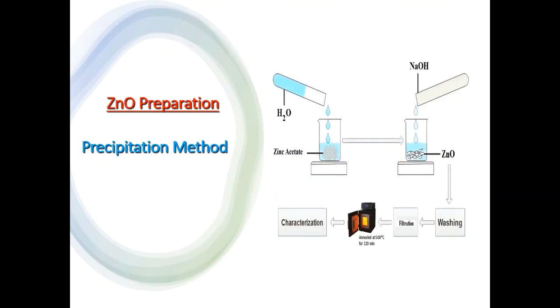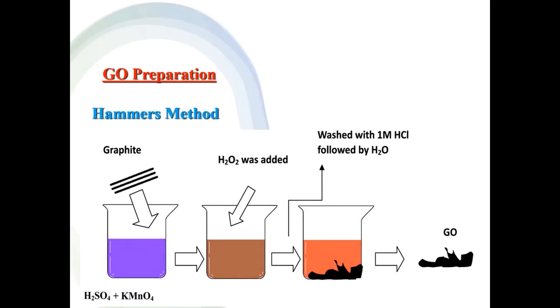So to achieve our aim, we prepared our samples as follows. For nanomaterials preparation, the precipitation method was used to make zinc oxide with zinc acetate as a metal salt and sodium hydroxide as a precursor. Also, graphene oxide was prepared using the Hummers method using a mixture of sulfuric acid and potassium permanganate on graphite.